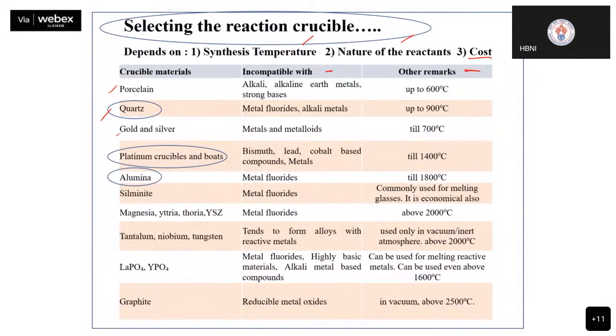Taking three examples, which you will most often probably use as a solid state scientist. Quartz we use only if we have to do synthesis up to 900. But then you have to take care that they are reactive with metal fluorides and alkali metal. Okay, if you have these, don't use quartz. Platinum crucible, very, very reliable crucible. You can go up to 1400 with them, but after that the platinum starts becoming softened. But make sure that you're not using bismuth, lead, cobalt-based compounds and metals.